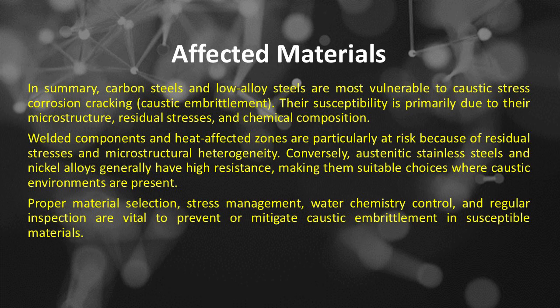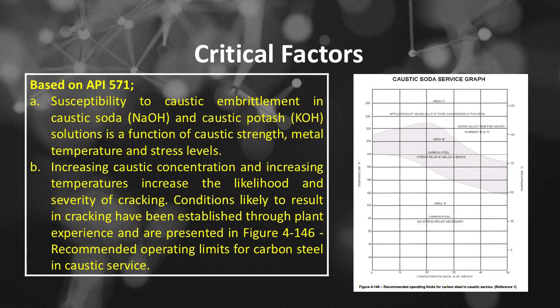In summary, carbon steels and low-alloy steels are most vulnerable to caustic stress corrosion cracking, caustic embrittlement. Their susceptibility is primarily due to their microstructure, residual stresses, and chemical composition. Welded components and heat-affected zones are particularly at risk because of residual stresses and microstructural heterogeneity. Conversely, austenitic stainless steels and nickel alloys generally have high resistance, making them suitable choices where caustic environments are present. Proper material selection, stress management, water chemistry control, and regular inspection are vital to prevent or mitigate caustic embrittlement in susceptible materials.